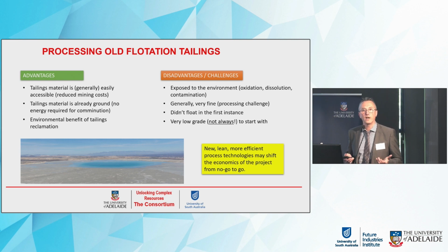If you have particles finer than 5, 6 microns, as sometimes you have in tailings, they are more difficult to float. And of course, the first comment is, well, that stuff didn't float in the first instance, why should it float now? But we hope that now we have better technologies, and we know how to address things that maybe 20, 30, 40, 50 years ago, they were not able to address, and that's why that material ended up into the tailings dam.